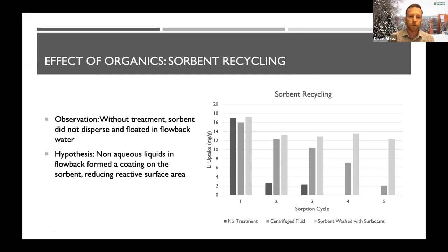So a couple problems here. I'm going to come back to that dissolution of the manganese, but what we did observe when we put the sorbent, the powder, into the brine, even after the centrifugation to remove the particles, even after pouring off the hydrocarbons at the top, is that the sorbent sometimes would not disperse in the solution. It wouldn't sort of distribute itself in the solution. It would float on the top. And the issue here, our hypothesis was that there were still non-aqueous liquids in there, so hydrocarbons essentially, that were forming a coating on the sorbent and basically blocking its surface. And we can see that if we look at the data.